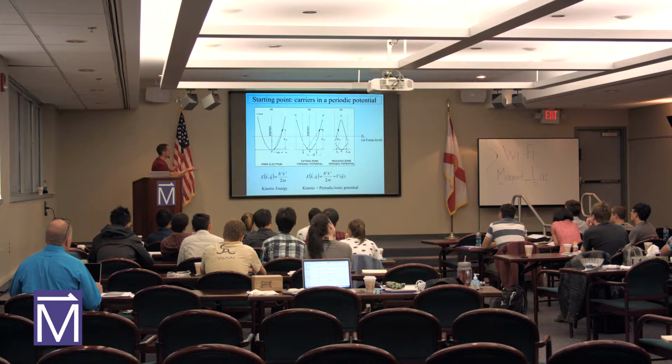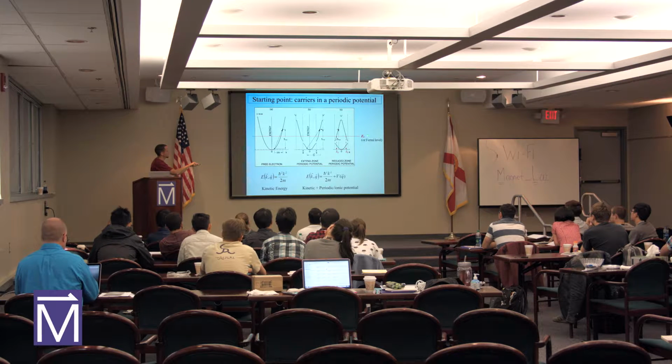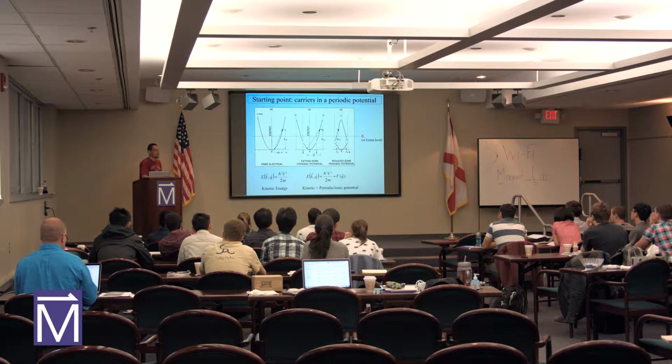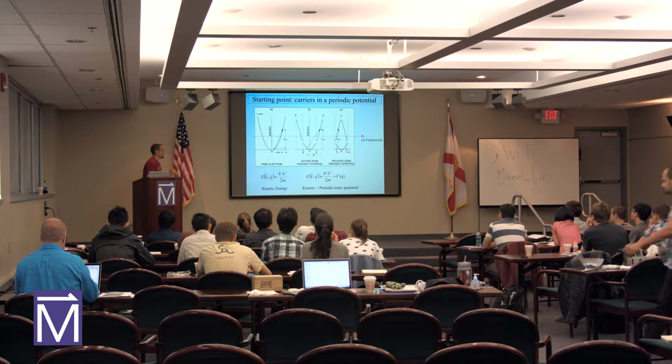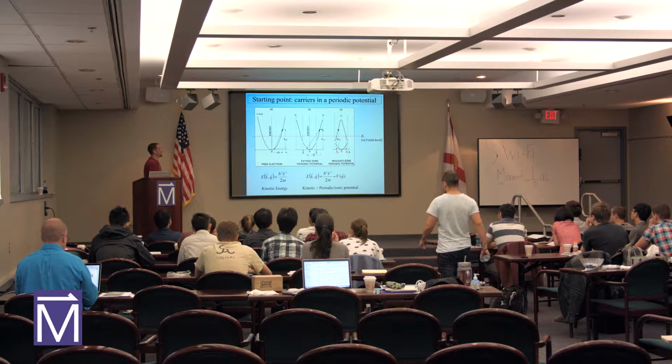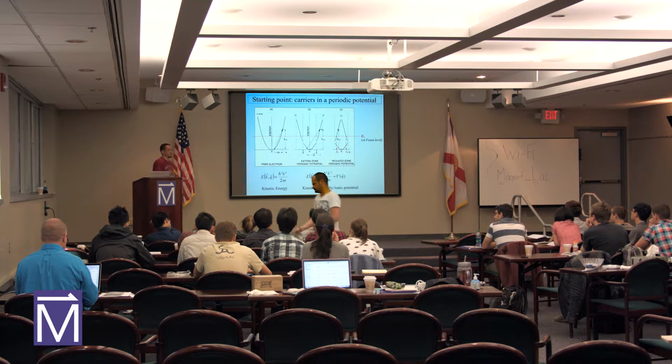But where the energies actually move and interact is at the Fermi level. So if we have the Fermi level going through an energy band in the middle, it's a partially filled band. And that means that the electrons can move around. They have the possibility of shifting energy. If the Fermi level goes between energy bands, then we have a completely filled band and a completely empty band, and there's not the possibility of electrons moving around. So this describes why a material is either an insulator or a metal. Partially filled bands give us metals. That doesn't really tell us, though, what a Fermi surface is.